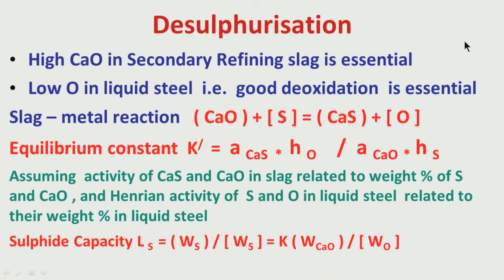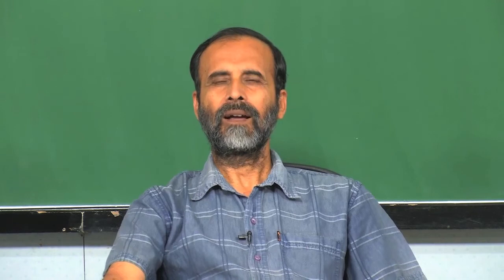Now, what is desulfurization? Let me first talk about that. Desulfurization basically means removing whatever sulfur is present in liquid steel after primary steel making. As I have told you, since there is a lot of iron oxide in the primary steel making slag, the dissolved oxygen level is also very high, and if the dissolved oxygen is high, desulfurization is not very effective, which I have already discussed earlier, and today I will come to it in a more elaborate fashion.